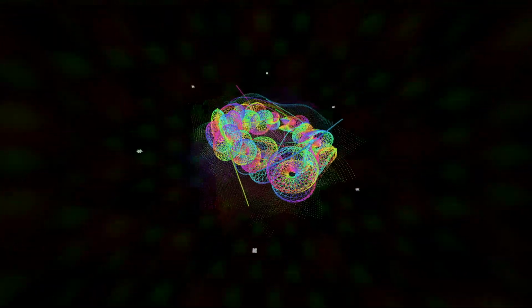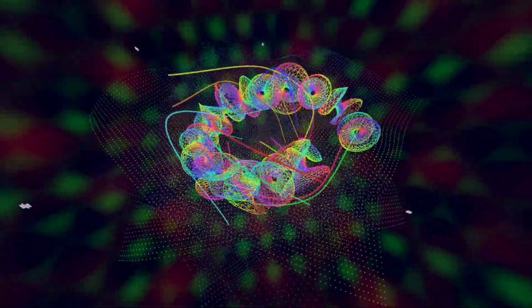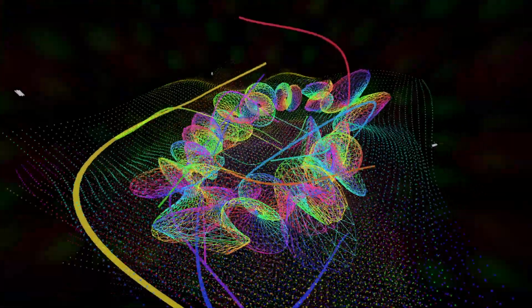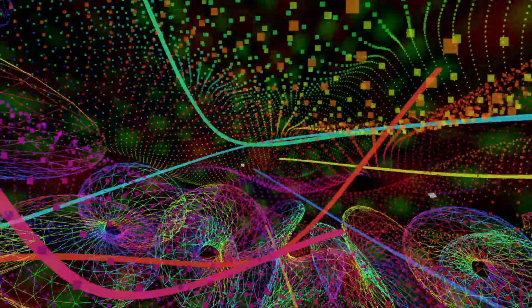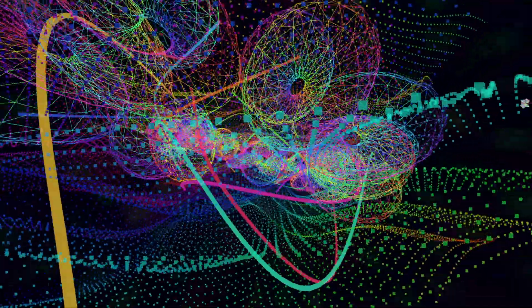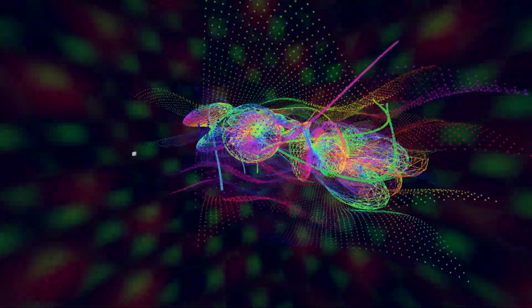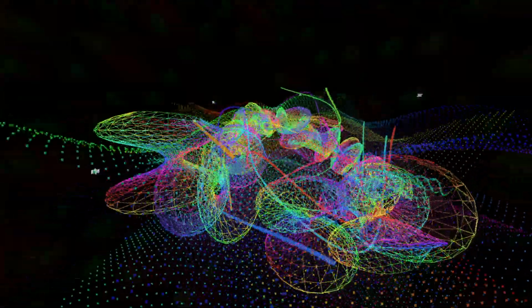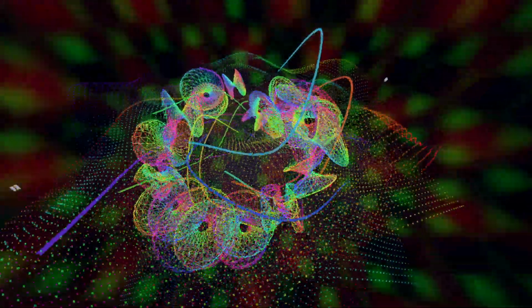Then there's broadband absorption. The wasted infrared light covers a pretty wide range of wavelengths, but many current upconverter materials only absorb strongly in very specific, narrow bands. So they only catch a small fraction of the potentially usable IR light. Exactly. You want something that can gobble up a much wider slice of that wasted spectrum. And then the light they emit, the upconverted photon, its wavelength, needs to be perfectly matched to the solar cell, ideally just above the cell's bandgap energy. Too high, and you just reintroduce thermalization losses in the cell itself. Getting that precise tuning is hard.